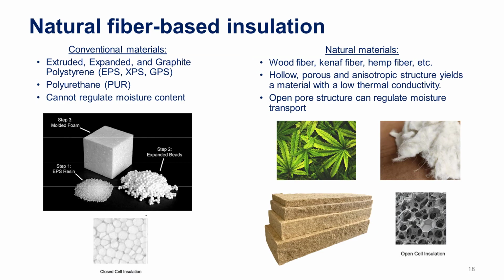For the insulation, again, I told you currently it's this polystyrene type of closed cell insulation, meaning that it really cannot regulate relative humidity or moisture. And so a lot of times you can form mold on those surfaces. And so instead what we're looking at is natural fibers, which inherently have a hollow structure. And so, for example, wood fiber, kenaf fiber, hemp fiber, and this is hemp fiber from our lab. These are hollow materials, porous, and anisotropic, and all of those are exactly the properties we need in order to get to very low thermal conductivities.